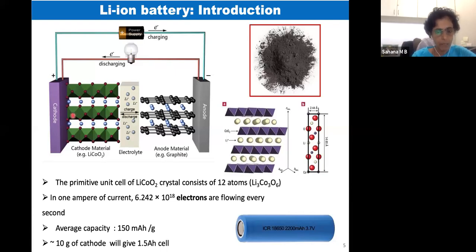As you can see here, when you want charging and discharging to happen, the electron from these cells or this cathode material has to go all the way to the cathode current collector. What we are showing here is only a couple of angstrom, but the actual thickness of the electrode, once these powders are coated over the current collector, is around 100 micrometer. So the one at this end, around 100 micrometer away from the current collector, the electron has to pass all the way from here to this. So the conductivity should be very good. To do that, we have what are called conductive additives, which is usually carbon black. Now that is about the current I have talked about.